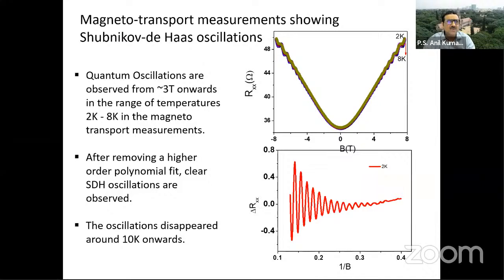Now if I look at the magnetotransport of this material, if I measure the resistance as a function of applied magnetic field, you see that above a particular field, you start seeing nice oscillations. On either side, you see very nice oscillations, so you can appropriately remove the background. Once you remove the background, you see these Shubnikov-de Haas oscillations in this material.